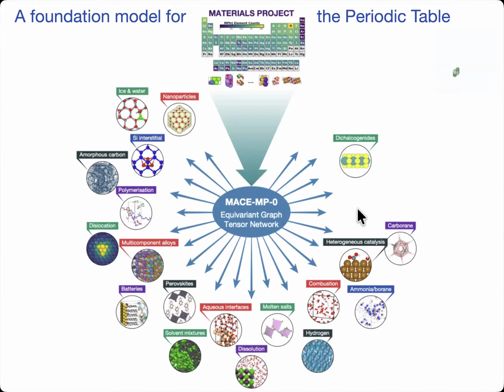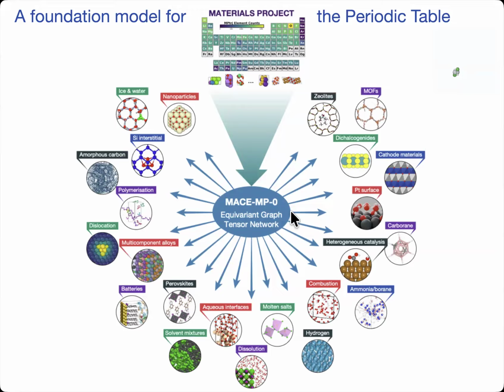And the astonishing observation was that the model trained on small inorganic crystals was stable at high temperature MD in all of these materials, and roughly the right things happened. Hydrogen got combusted, heterogeneous catalysis happened with typically reasonable barriers, and salt dissolved in water in approximately the right mechanism, and so on. And before that, before these equivariant graph neural networks, before the MACE model, this was not the case. So you couldn't take a model fitted on small crystals and go and do materials chemistry with it.